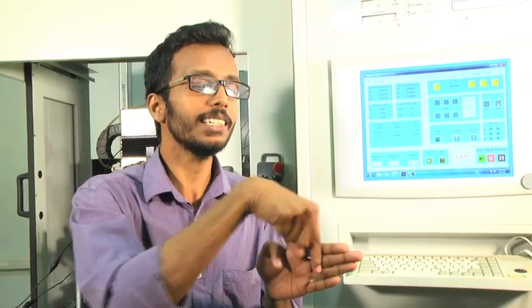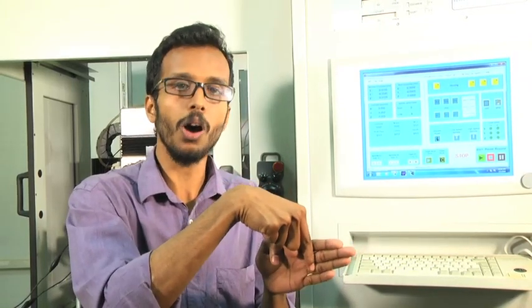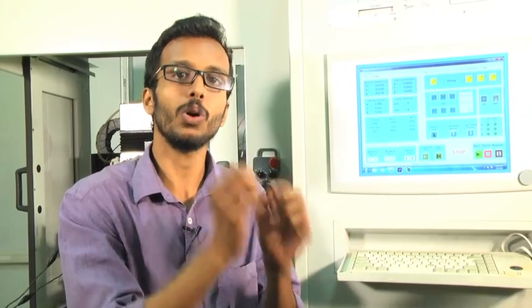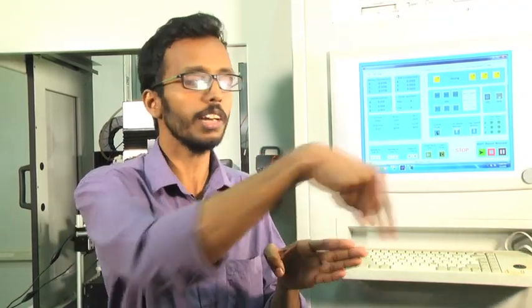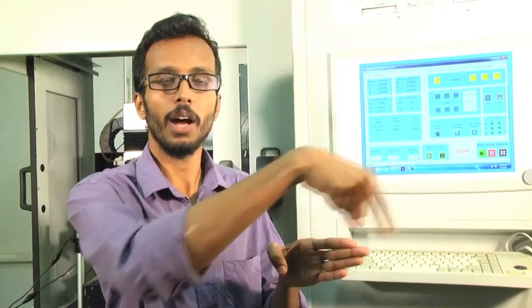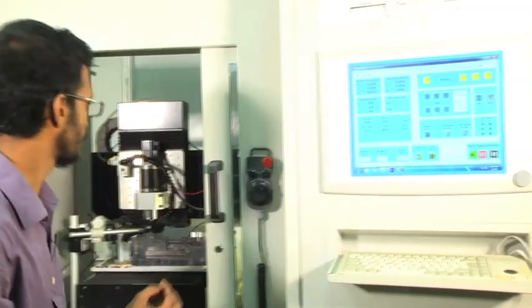The contact probe method will find out the touching point by when the shorting occurs. We will be moving very near to the standard piece or the tungsten carbide block, and as it touches the block, there will be some shorting, and that point will be taken as the contact point. Just remember, we will be touching and then moving 150 micron inwards, and we will be moving in the y direction, so that the diameter will be reducing. Next I will explain how to use the contact probe method.